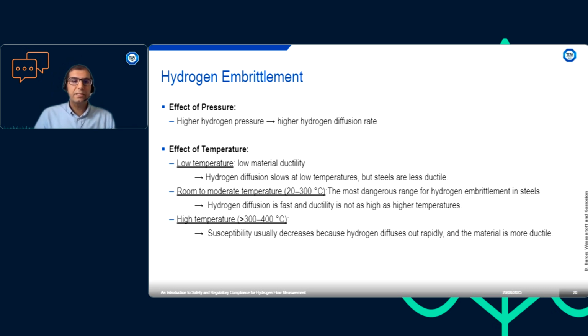So what is the effect of pressure and temperature on hydrogen embrittlement? Basically, if we have a higher pressure, we will have a higher hydrogen diffusion rate. So basically, it means more hydrogen will diffuse into the structure of the material and will cause more problems. So if your system works at a higher pressure, there is more risk of hydrogen embrittlement.